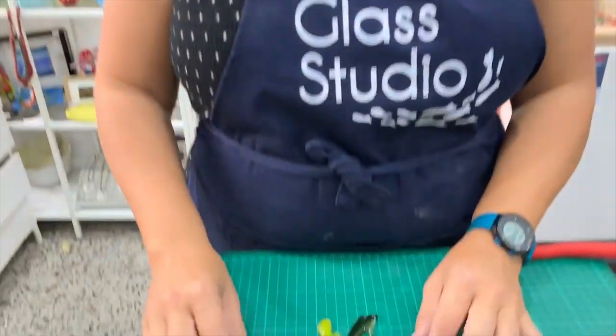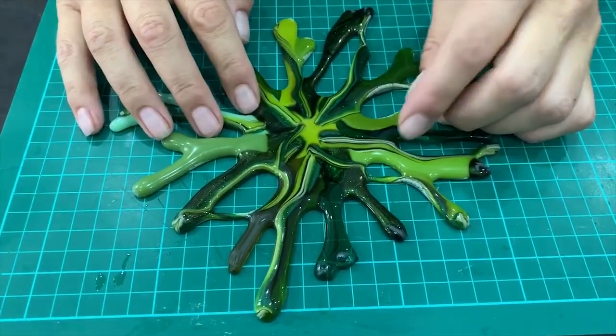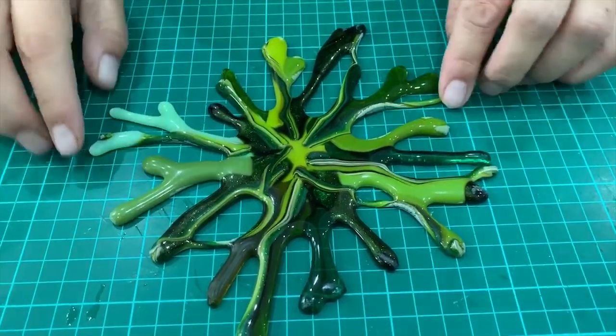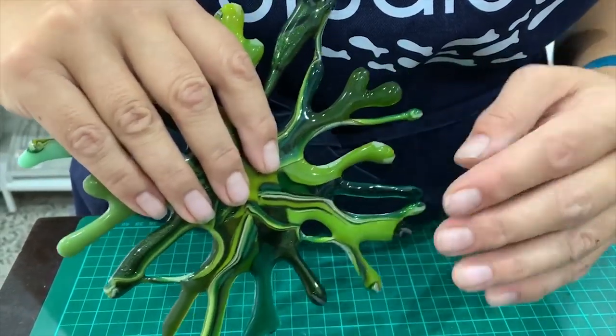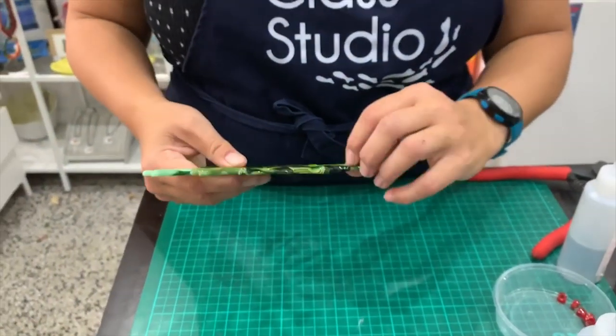So this one, we've now got this out of the kiln. Little bit of an issue. I put this on thin fire. Guys, it's much better when doing this kind of project to use a kiln wash kiln shelf, not thin fire, because we've got this, which is basically where the powdered paper has stuck to the glass as it's sort of rolled up to become 6 mm. And it's around here too.